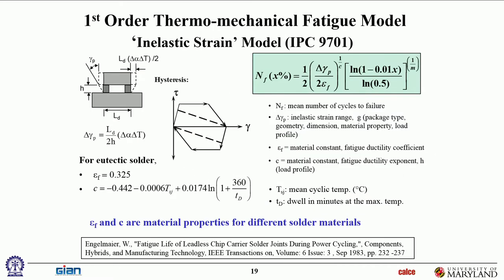And our method is not brand new either. I didn't invent any method. I just looked at the high temperature industry and I saw some of them. So if you look at the nuclear industry and the aerospace industry that have to design for high temperature structures, some of them use a similar approach. They call it the frequency adjusted fatigue exponent. They calibrate the fatigue exponents based on empirical data. Some of them use a different approach called strain partitioning. There they actually look at the strain range and they say, well, some of it is creep, some of it is plasticity, some of it is elastic. And they actually estimate what portion is creep, what portion is plastic. So my group uses that approach. We use the partitioning approach.